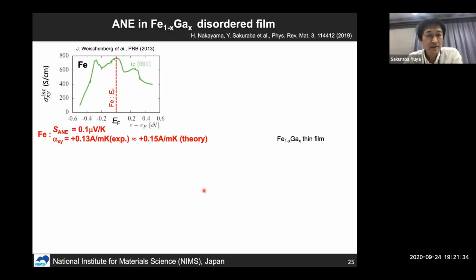However, if we measure the anomalous Nernst effect in pure iron, unfortunately, the obtainable thermopower of ANE is very, very small, just 0.1 microvolt per Kelvin, and alpha XY is just 0.1 ampere per meter Kelvin. This result can be explained by the intrinsic anomalous Hall conductivity. As you can see, in pure iron, sigma XY shows even-function-like behavior around the Fermi level. So the very small alpha XY is actually very reasonable.